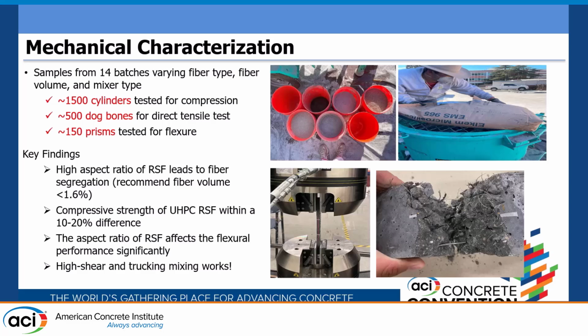We saw that the compressive strength is just a 10 to 20% difference compared to the manufactured fibers. It's not as bad, but of course we will see a decrease in compressive strength. Also, regarding aspect ratio, if we use a low aspect ratio for the recycled fiber, it's going to affect the flexural strength a lot.